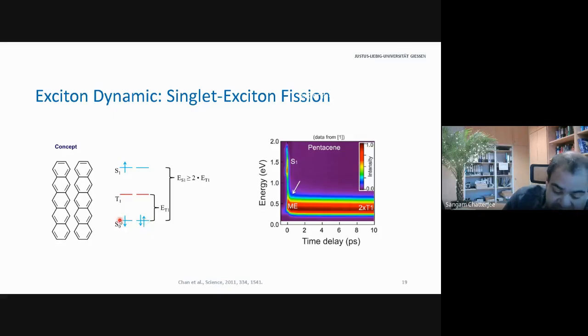You might know from your atomic physics class that in molecular systems or in solids, you can have singlet transitions, which are typically optically allowed, so they're dipole allowed. But due to exchange interaction, you can also have other spin configurations where you don't only have a spin flip from down to up during the excitation, but you can also have a triplet excitation, which is dark, so it's dipole forbidden. In these triplets, you can have 2 spin up or 2 spin down, which are 2 of the triplet states, and a more intricate linear combination of spin up and spin down states, which makes 3. These are energetically degenerate as long as you don't have a magnetic field, but they're typically at lower energies in systems with strong correlation effects, like molecular solids actually do.